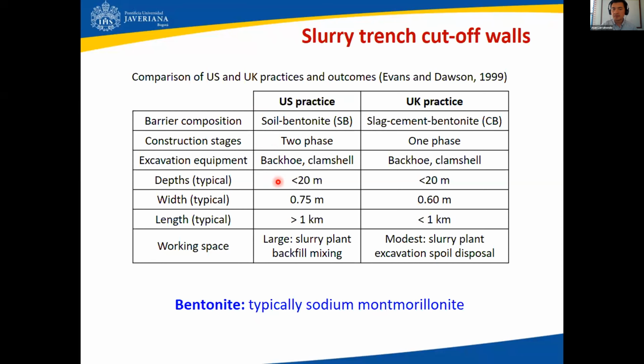The depths are also similar, less than 20 meters, typically for these types of walls, but the width is a little bit larger in the US, in soil bentonite rather, about 75 centimeters, whereas in slag-CB it is typically 60 centimeters. Also, perhaps a major difference is that typically the lengths of these walls are longer in soil bentonite systems, more than 1 kilometer, than they are in slag-CB systems. And another major difference as far as logistics of construction is that the working space required for the implementation of the systems is typically larger for soil bentonite slurry trench cutoffs because they use slurry plant backfill mixing, whereas for slag-CB systems it is rather modest because they use slurry plant excavation and spoil disposal.